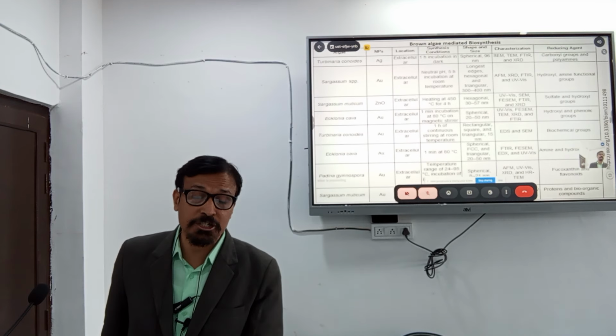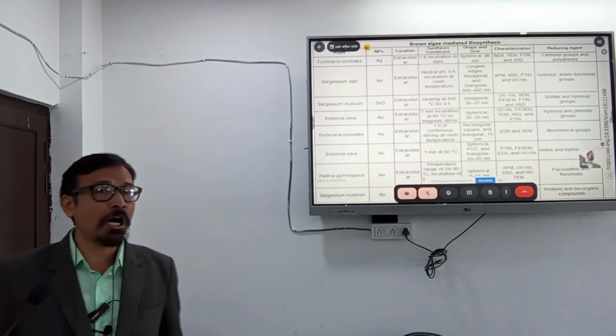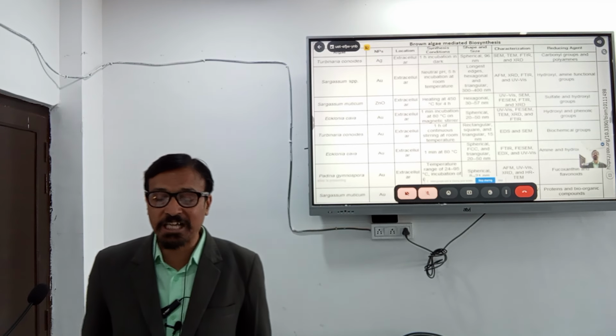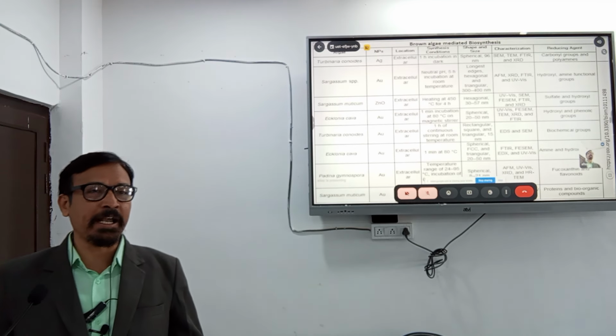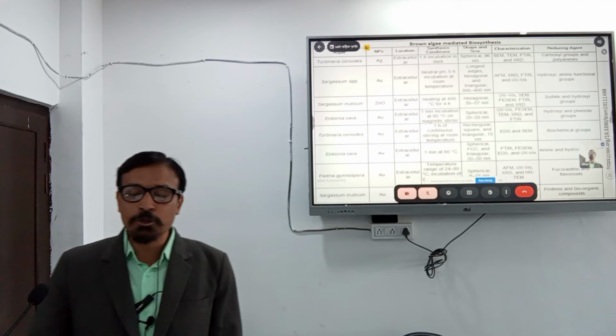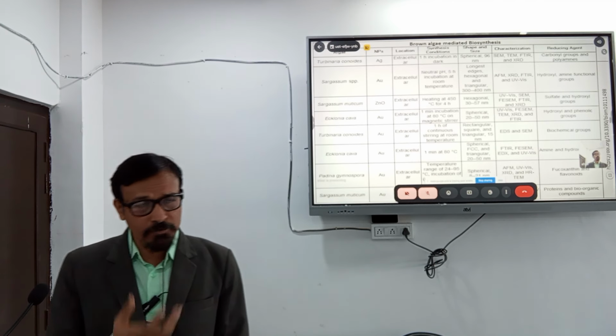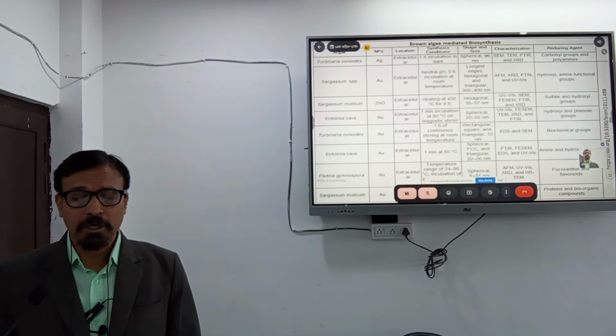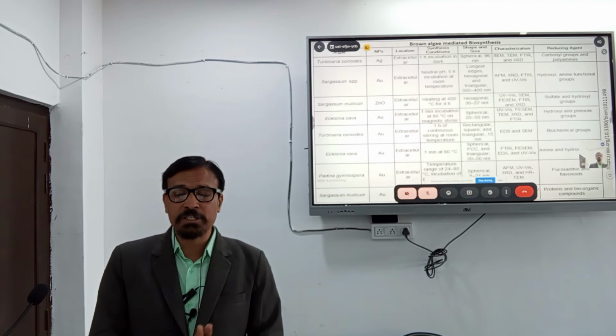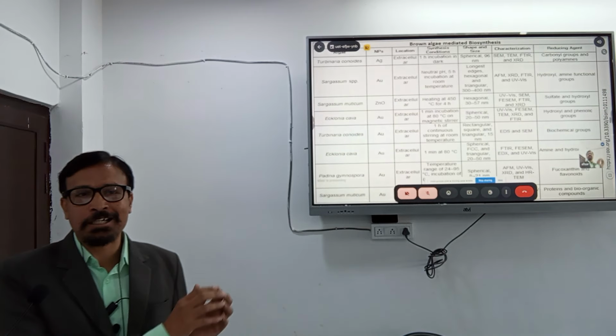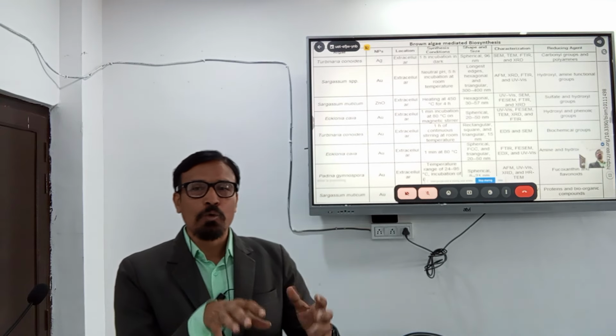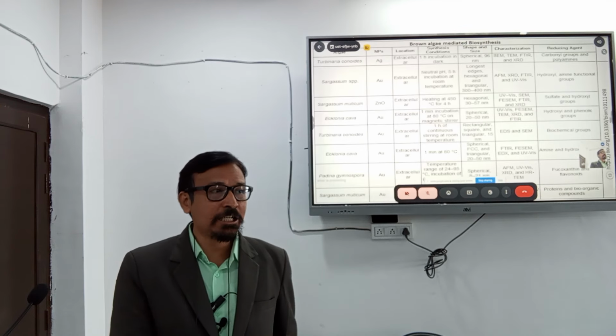The location is extracellular, and the synthesis condition is 1 hour stirring at 45 degrees Celsius. And the FCC spherical nanoparticles will be produced in the range of 6 nanometers, and zeta potential and UV-vis TEM can be used for the characterization. So I included one more equipment, zeta potential.